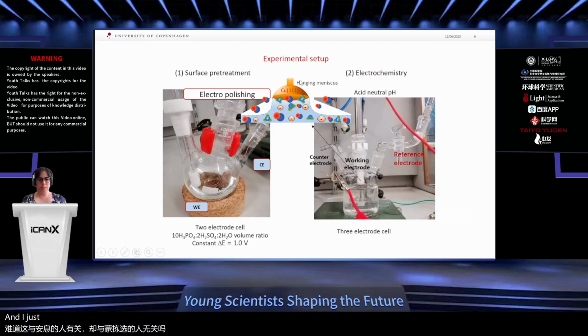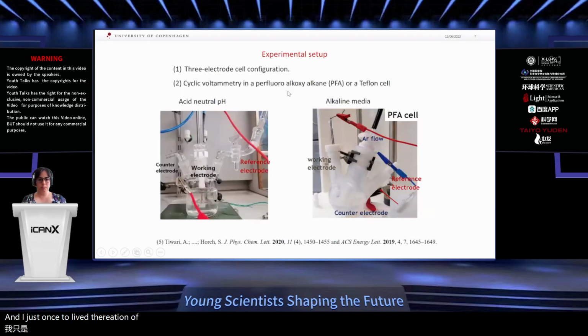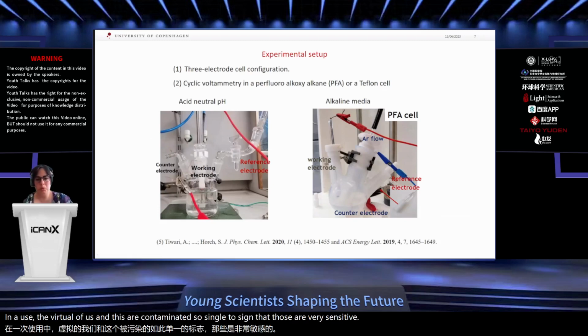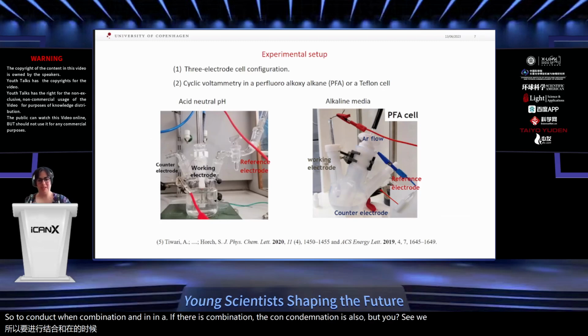And then, of course, depending on if I'm working in acid, neutral pH or in alkaline media, I use a purified gas, and this can contaminate the surface. So single crystalline electrodes are very sensitive to contamination, and unfortunately, if there is contamination, the contamination is also reproducible on CVs.